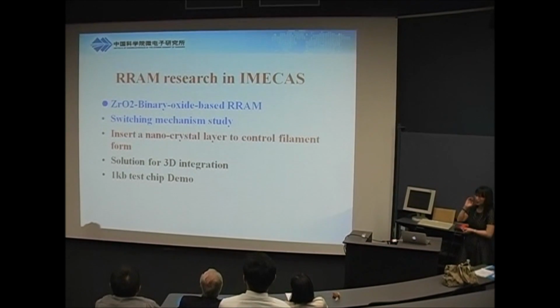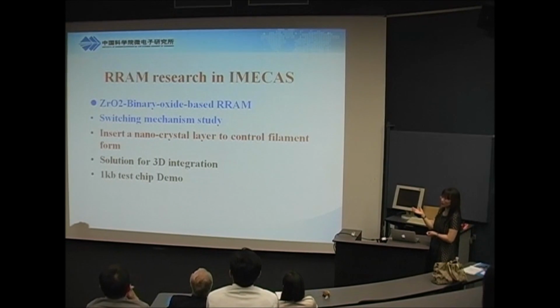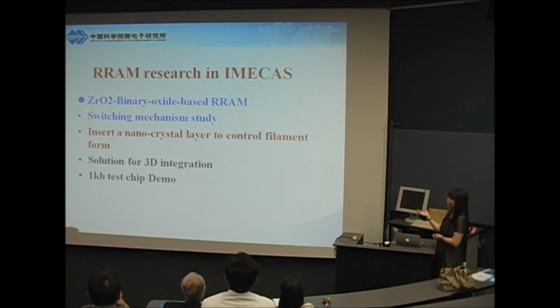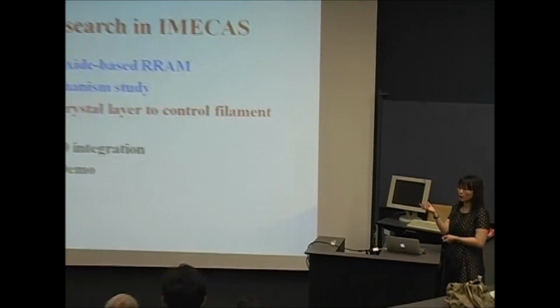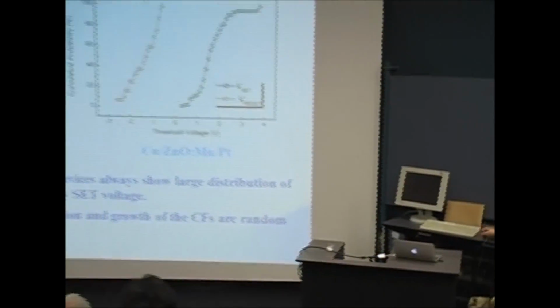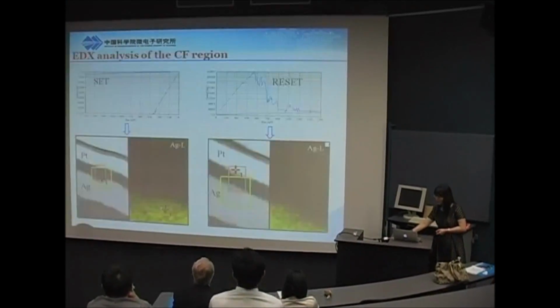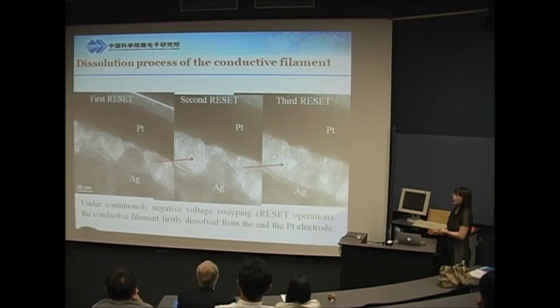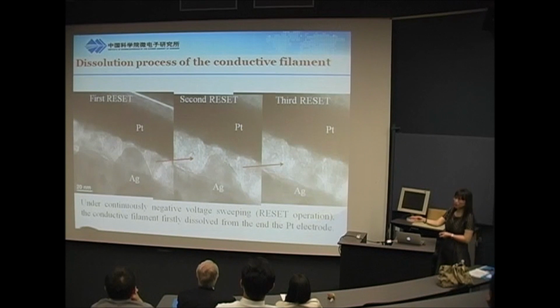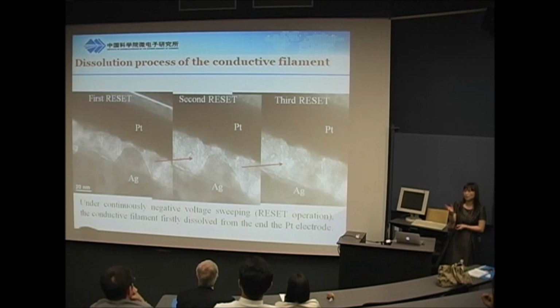So this is a mechanism. Either from the electrical measurement or from the TEM observation, we can confirm that the metal filament forming and rupture process is responsible for the switching on and switching off of this kind of device. But another problem is, as we mentioned, there is a big variation for this kind of device. The reason is very easy. From this picture, we can see this filament forming process is random. You cannot control at what location the filament forms, or at what time the filament forms. So that's why the parameters have a large distribution.